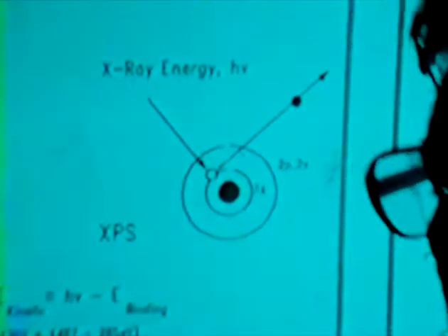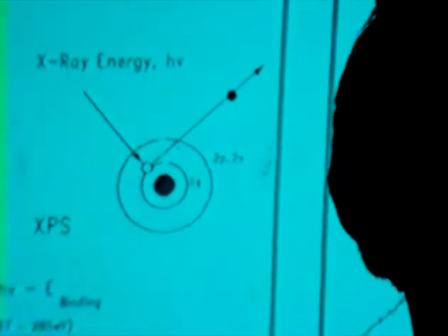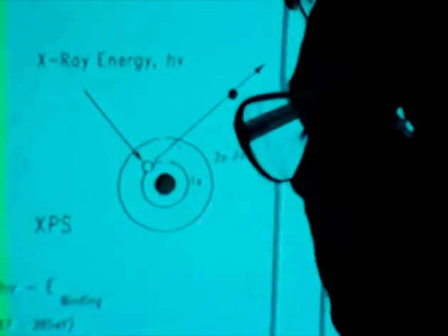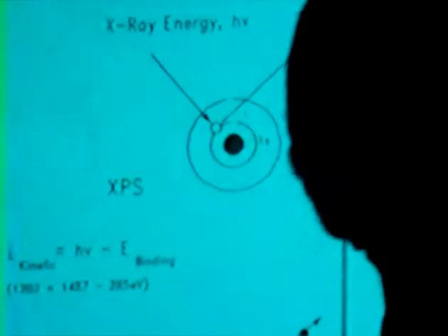Now the electron spectroscopies I shall talk about are of two kinds. One, the photoelectron spectroscopy, where you excite the electron with a photon. The photon is absorbed completely, so you have a unique energy in the outgoing single electron. So it's a one electron event with a unique energy there, and you can measure directly the binding energy of the electron in the orbital. And the spectrum from that is a very nice one, because it's got these very sharp photoelectron peaks, which we can use for very good chemical state resolution.